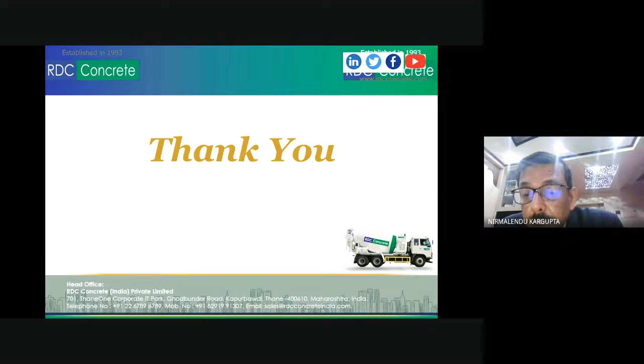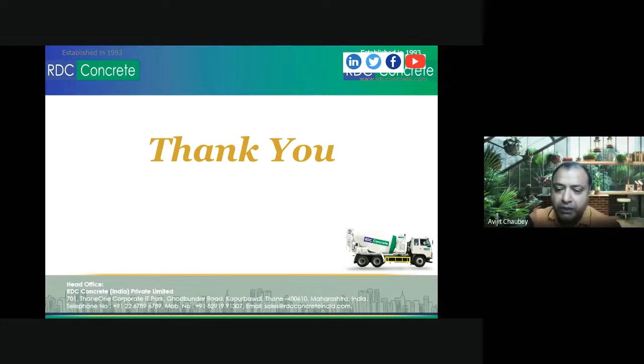Lalit Kele asks: if we are using ultrafine percentage in the mix, do we need to increase mixing time while batching? May not be required. But if you are going beyond a certain percentage, let us say a very high percentage, I would mean above 5%, yes, in that case, mixing time may increase. Or if you want to reduce the mixing time, a good admixture is what will reduce the mixing time.